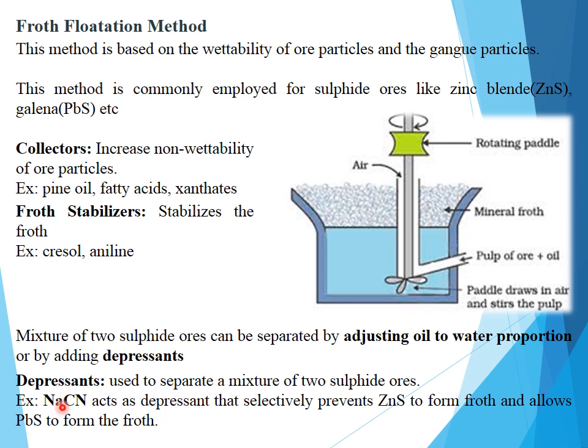When you add sodium cyanide in a mixture of these two sulfide ores, sodium cyanide combines with zinc blende, that is, it combines with zinc and forms a complex, a coordination compound, which will reduce the froth formation capacity of zinc blende. Hence, it will not form a froth, whereas the remaining part, galena, that is PbS, will combine with these collectors and form the froth and come to the surface. In this manner, sodium cyanide prevents zinc blende from forming the froth and allows galena to form the froth.